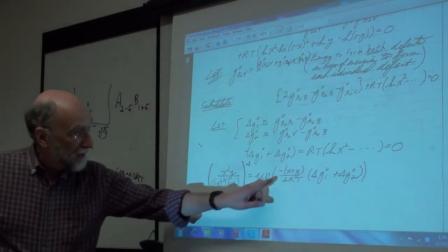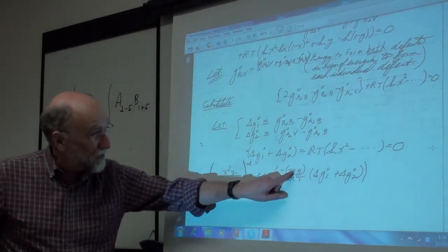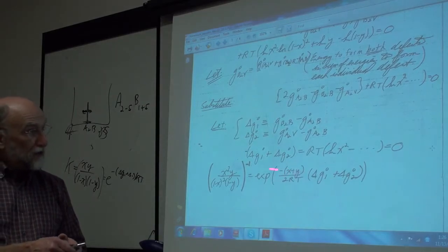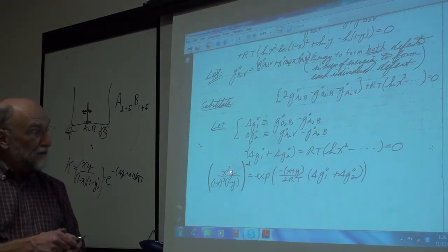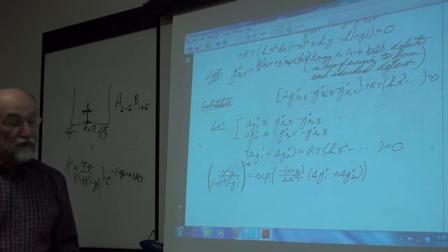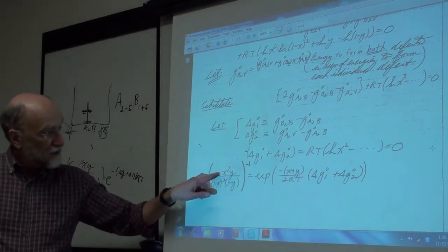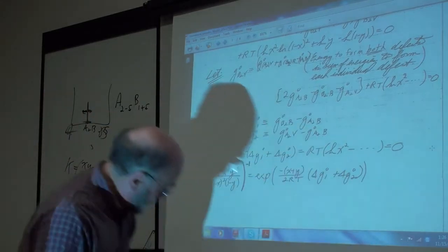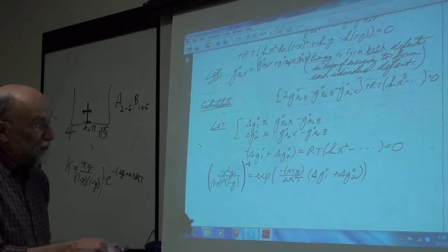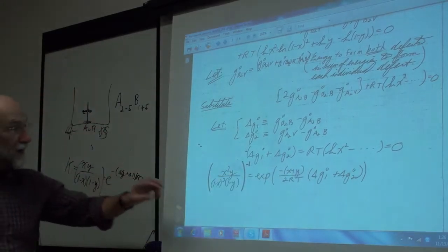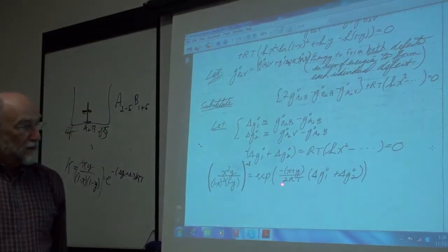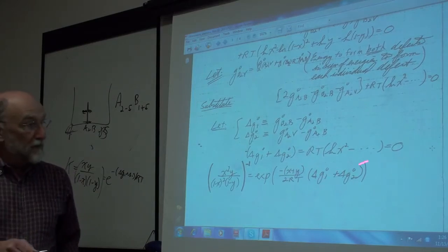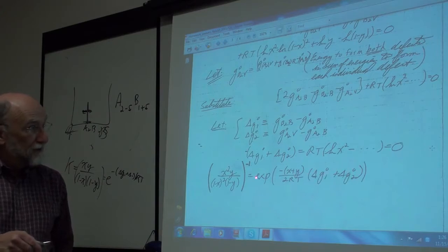And you'll see too when you do this that whatever you end up with in here is always quite small. X and Y are small, they're the vacancy, the defect concentrations. Okay, the defects are there in small amounts, so the X and Y are quite small. So whatever you get here, this x plus y, there'll be something here which has to do with the mass balances, but that will always be reasonably constant. The delta G1 and delta G2 are your main thing. So this whole thing is pretty much constant.